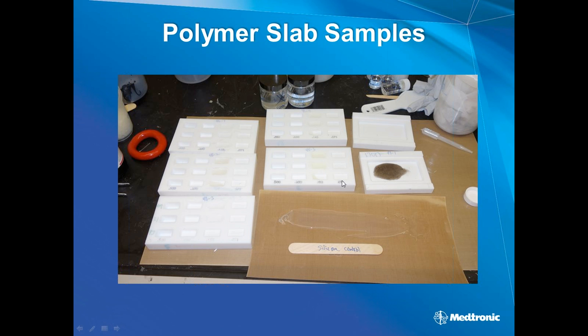and they're kind of difficult to see probably, but they're different wells in the top of these of different depths, and we use the shallowest ones, and I think these are about a ½ inch by maybe 1.5 inches, and maybe 3/16 of an inch thick. And so we fill these, we mix up solutions, and it's almost like a shake and bake routine of these different polymers we've been working with, and these are actually cured at room temperature.